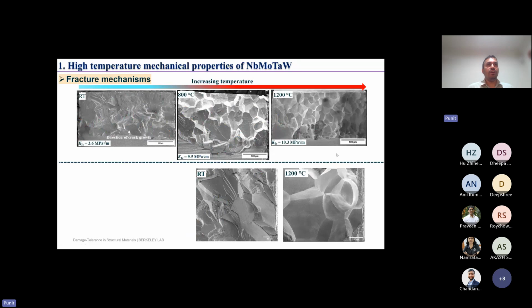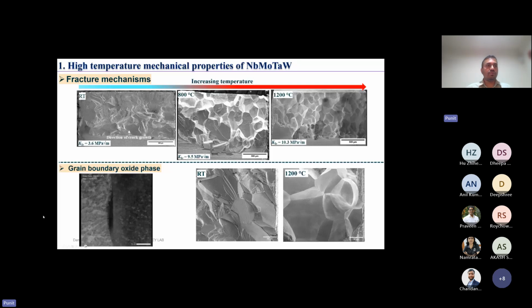So this was really interesting to us, and we wanted to understand what is exactly going on. So we looked at the fracture surface of this material, and we see that at room temperature the material fractures by these cleavage fractures, but with increasing temperature you can see the fracture mode is now a mixture of cleavage and intergranular. At 800 degrees C, at 1200 degrees C, we see complete intergranular fracture, and you can see here that these cracks, actually these river marks, emanate from the grain boundary. So there is something going on at the grain boundary, and at higher temperature the grain boundary is so weak that we are getting intergranular fracture.